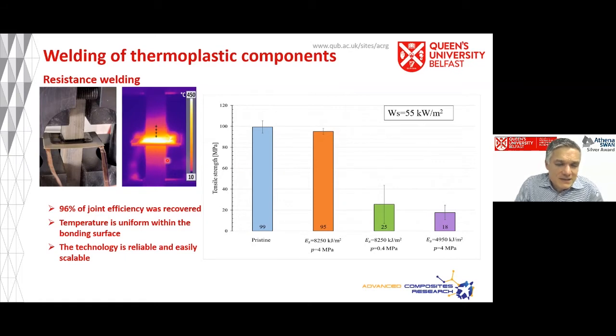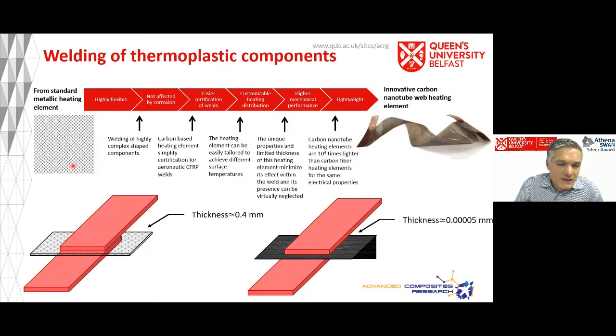Now, what's nice about this is that unlike, say, places where we know thermoplastic welding is being achieved by the insertion of a metallic heating element, which then remains in the structure, when you look at what happens to our web, you can't even see what happens to the web once the two surfaces are fused. So it almost disappears, which is actually quite a nice thing to have.